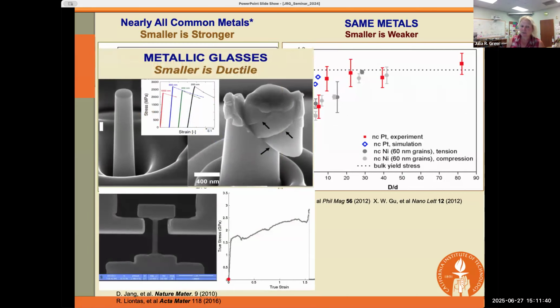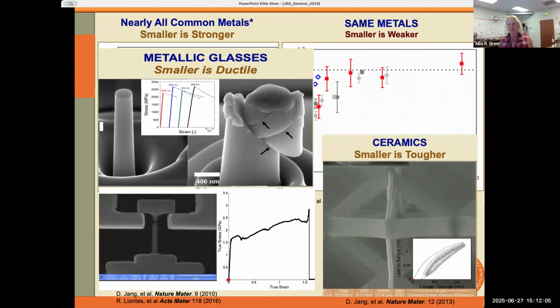Now, the size effect is even more interesting than that. If you look at a brittle material like glass, for example, what I'm showing you here is a uniaxial tension experiment on a 75 nanometer wide glass rod. And you can see that it's first forming a neck prior to fracture, and it extends by about 100%. So at room temperature, we all know glasses are not supposed to do that. So yet another interesting effect that emerges at the nanoscale. And this is the last example. When you look at a ceramic nanolattice, and this is a single unit cell, what we're doing here is deforming a single unit cell, and we're observing that these very brittle ceramic beams are bending without fracturing.